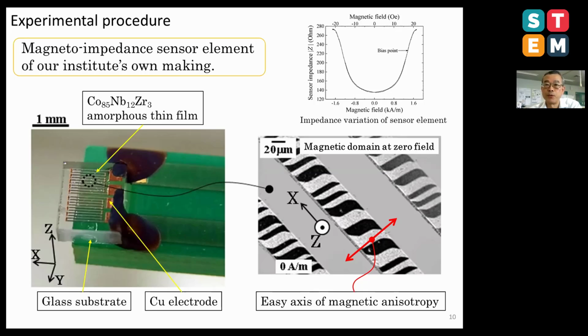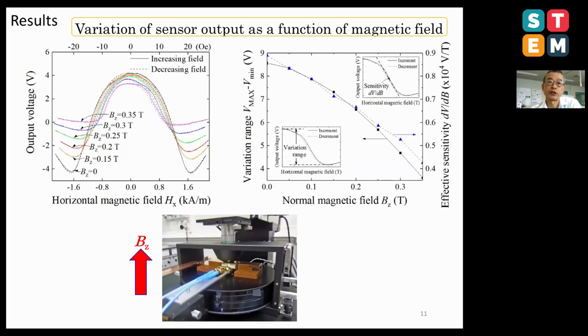The sensor has a meander configuration and is connected to the printed circuit board, and then it was connected to a driving circuit. The magnetic domain at zero external field is shown on the right, and the impedance variation as a function of the sensing field is shown above. This profile of impedance variation is a typical one of the thin film magnetic impedance sensor. The sensing direction of the sensor element was the in-plane length direction, the x direction. From here, the results are shown.